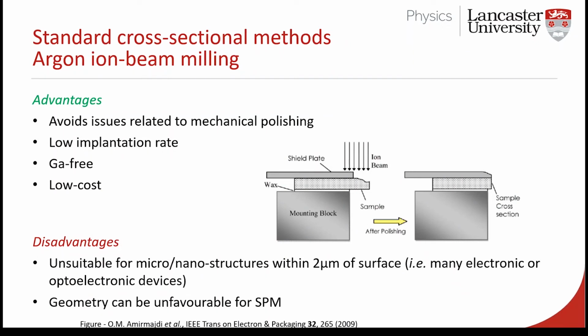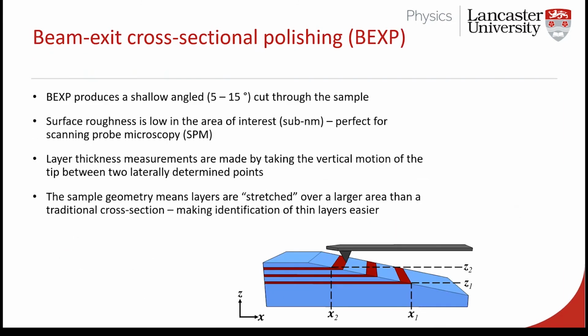So the real stroke of genius that my colleagues had was to angle the sample very slightly. And this is a technique, again, that's available through GISMO and other routes through the department. Again, I would encourage you, if this is something of interest, to contact Alex Robson directly for more information about this. So by angling the sample slightly, I've got a nice animation that shows this in a moment. The aim is that we're going to cut at a shallow angle, and we're going to elongate any buried features in our structures. So think laminate structures, composite structures. We're going to slice through that. We're going to elongate those samples, and that's going to make it easier to measure.